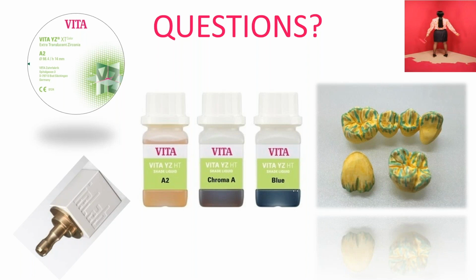What was the high temperature for reconditioning zirconia? If you're going to recondition it, that's 1,000 degrees for 15 minutes or so. That will be a good temperature in which you're going to restructure your zirconia so that you have a nice surface that is going to be conducive for porcelain layering. And then we have one from Jean. It's the VITA YZ XT is 3 mol. That is correct. The HT, the T and the HT are both a 3 mol.